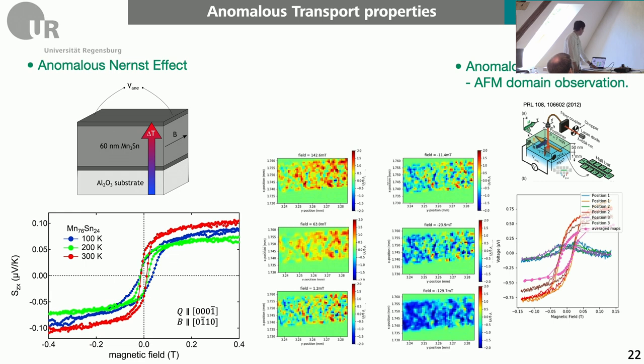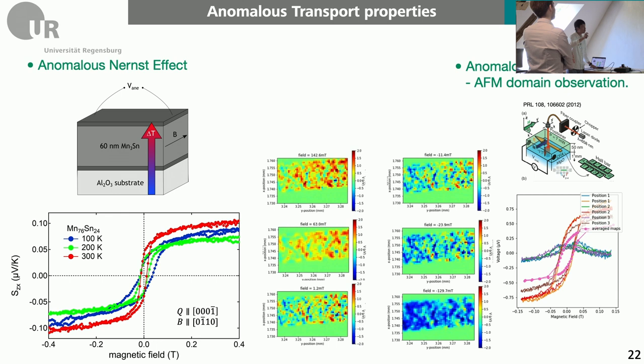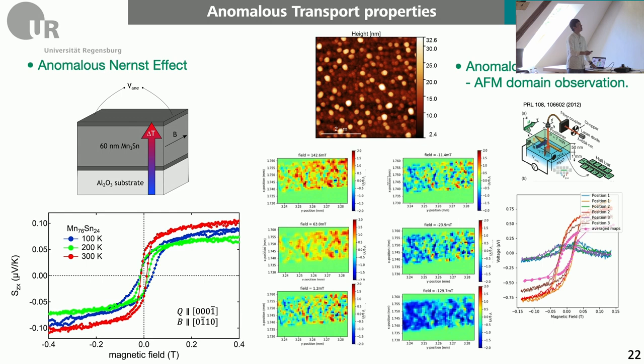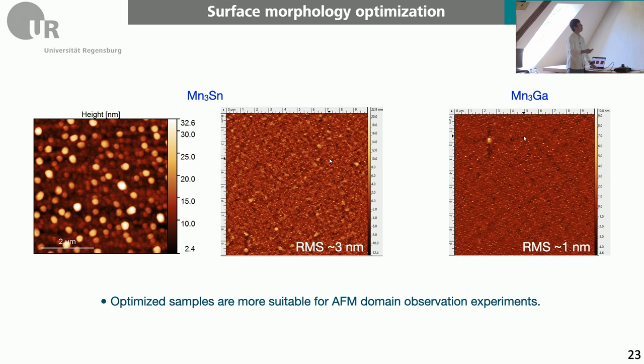We also measured the anomalous Nernst effect, which is shown here. We also tried to measure the domain structure by applying a magnetic tip from the top and scanning the surface, but the problem was the surface was too rough. It probably represents individual grain switching rather than switching of the domains below the rough surface. So we optimized the surface roughness quite significantly and are now trying to measure the domain structure using these well-optimized samples.